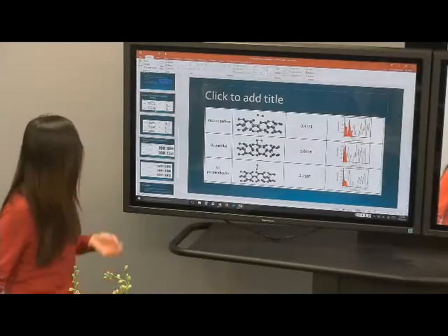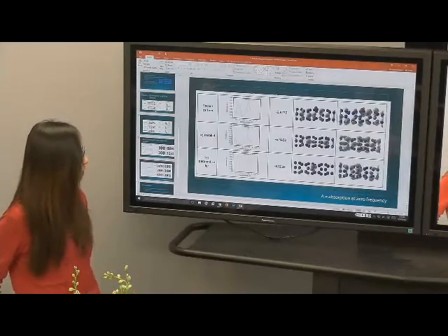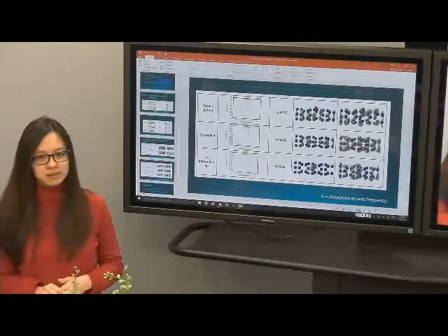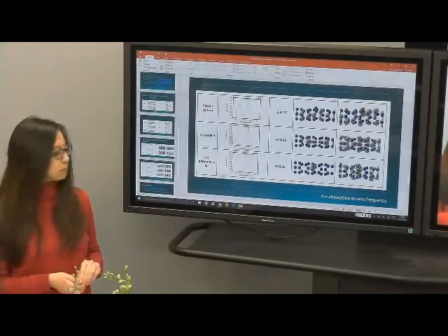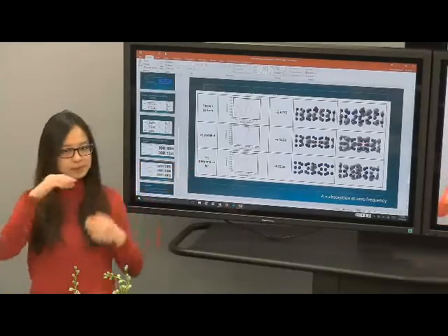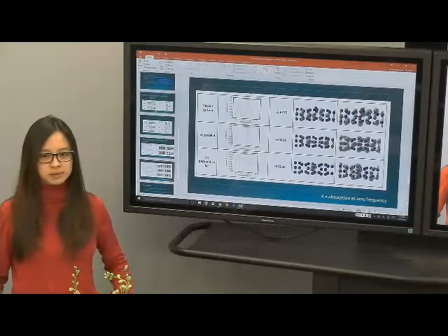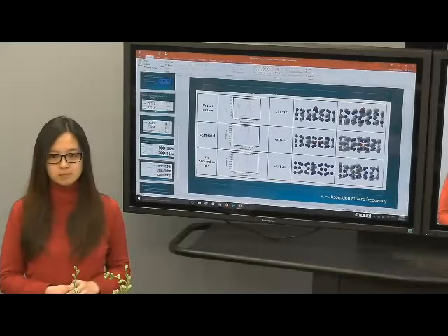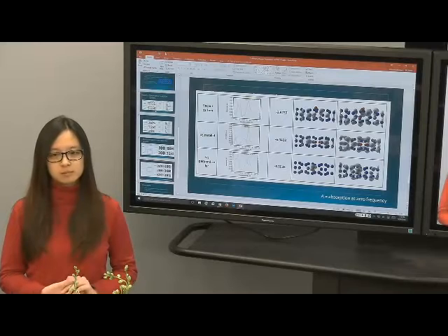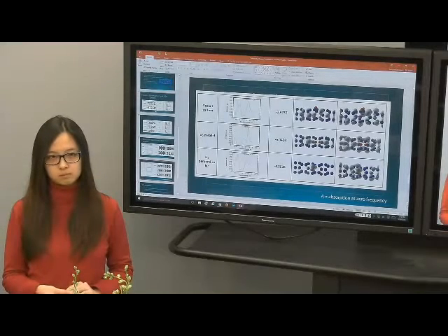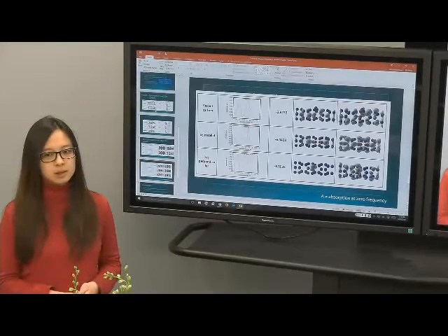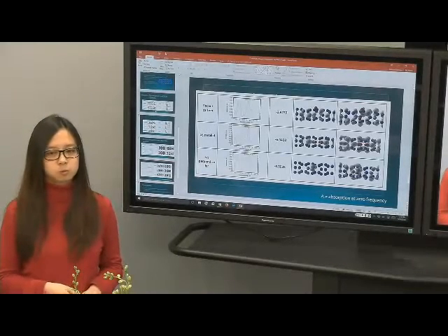So right, for the HOMO and LUMO, it does not change a lot except for this one. It has localized orbitals on the oxygen. In which case, when you substitute or when? No, the one that I put on top, just the normal. So when it's physisorbed, then you have very strongly localized orbitals, and these orbitals introduce this state inside the gap, right? In the other cases, when it's substituted, it's more delocalized over the surface, although the gap is still changing. Okay, so you have a different nature of these electronic states.